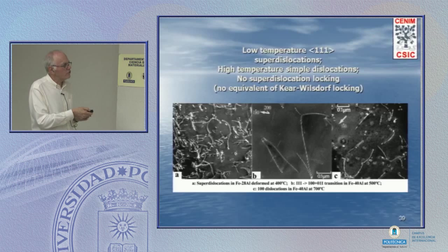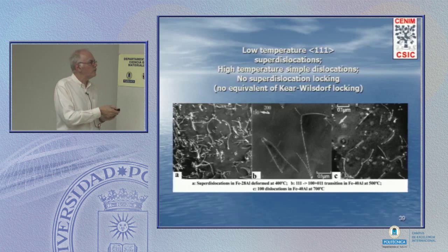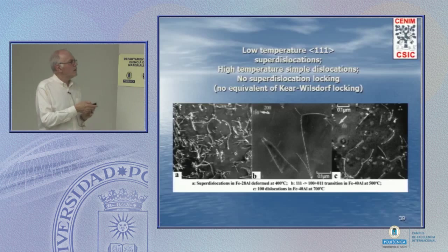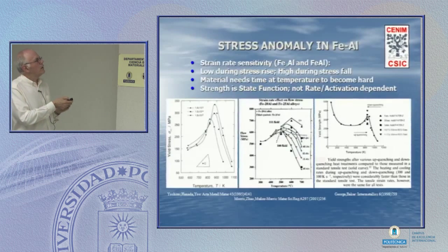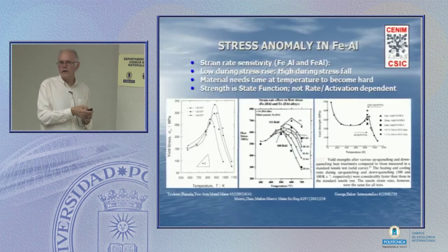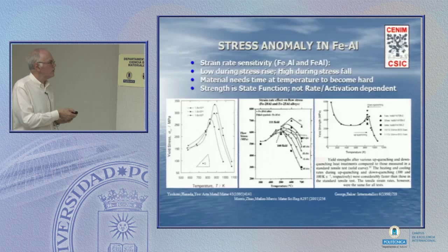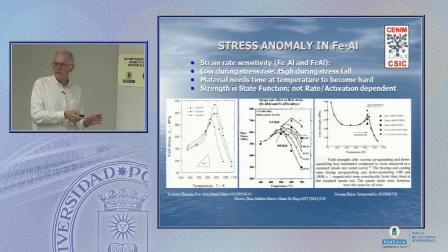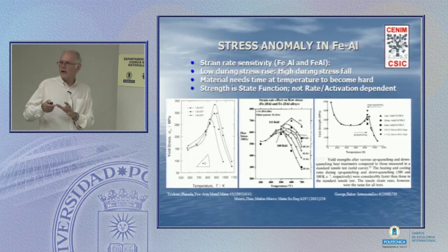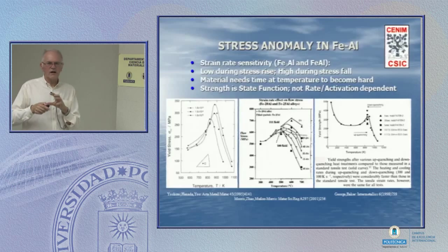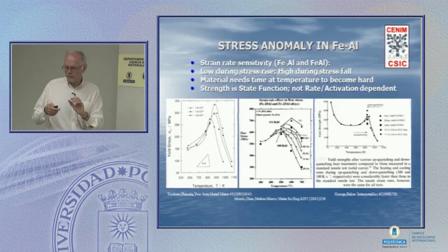Or here's a dislocation which, where it's bent over, is starting to decompose into two partials. And again, the partials don't want to move, so this is a pinning point. Now these sorts of pinning points give rise to a very strange behavior known as the stress anomaly that you find in very many of the intermetallics. And it occurs because the dislocations are complicated. At low temperature they glide as much as they can, but at high temperature they react together, form nodes that are obstacles, or decompose to become unmovable objects.